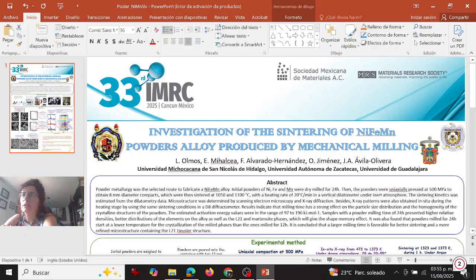Samples with a powder milling time of 24 hours presented higher relative densities, better distribution of the elements of the alloy, as well as the L21 and martensite phases, which will give the shape memory effect. It was also found that powders milled for 24 hours start at a lower temperature for the crystallization of the milled phases than the ones milled, for example, at 12 hours. It was concluded that a larger milling time is favorable for better sintering and more refined microstructures containing the L21 Heusler structure.